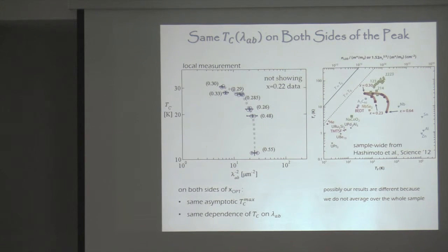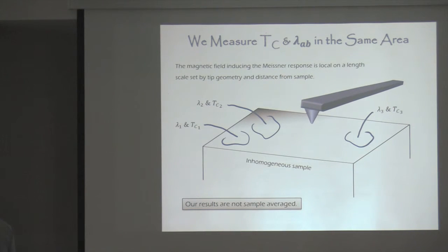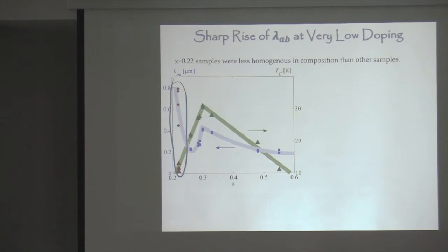Okay? So this is all the samples except for the really underdoped samples. And the thing is that the really underdoped samples turned out to be less homogeneous, and so if we measure at different points, we get slightly different values. So if we add those points to the plot, you can see that TC has a spread, and the penetration depth has a pretty big spread. And anyway, the values are really big.